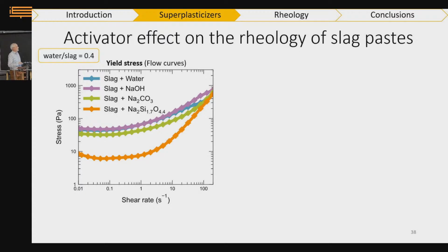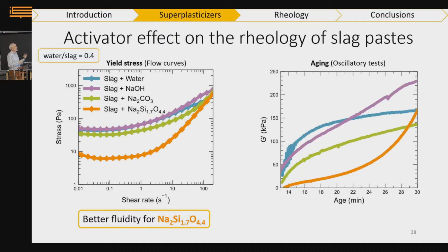Okay, a little pause. Now we go to the silicate. Silicate is another story because you see that silicate anions are already relatively good at dispersing, so the yield stress is depressed. So the issue in that case is not so much deflocculation, but more an issue of time evolution of the modulus. Here we plot the elastic modulus with time, and you see something very striking. I'm going to go very fast on this because they are models, but usually when you have stiffening of the contacts between grains, this leads to a logarithmic growth of the elastic modulus.